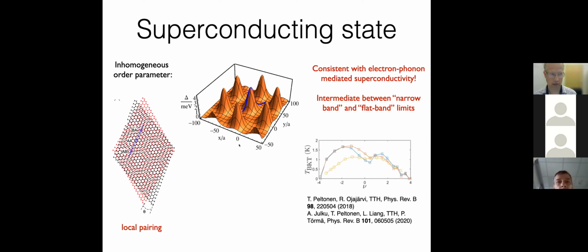Based on these BKT temperature studies and others, and comparing them to the experiments, first of all, we can state that this is consistent with electron-phonon mediated superconductivity, at least many of the studies point towards it. It is not for certain yet whether electron-phonon coupling is the origin of the interaction, but nevertheless.